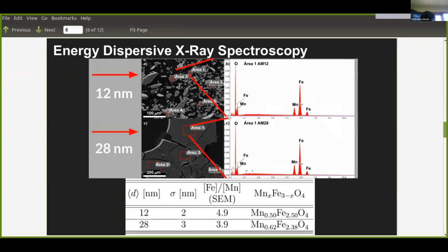These micrographs of the scanning microscope show randomly selected areas of a powder sample, where we take the spectra. The peaks found correspond to characteristic X-rays of the K alpha, K beta, L alpha, and L beta transitions. Then we estimate the atomic percentages from which we can determine the chemical composition.